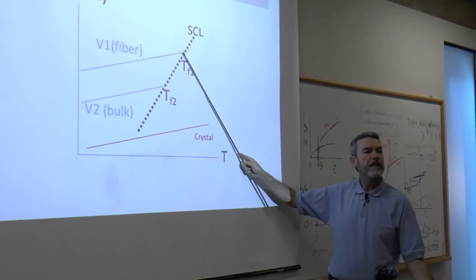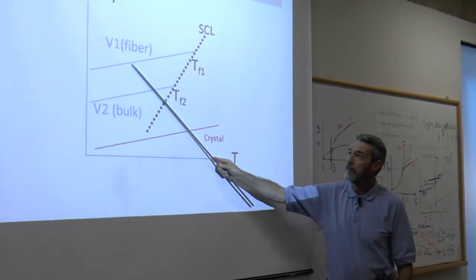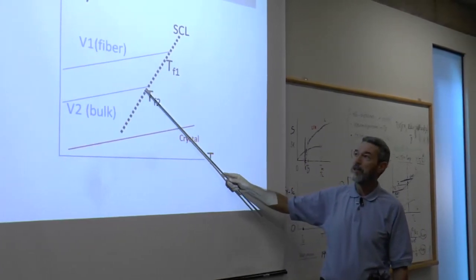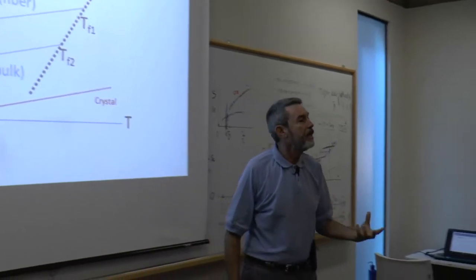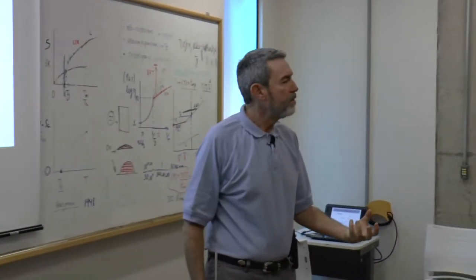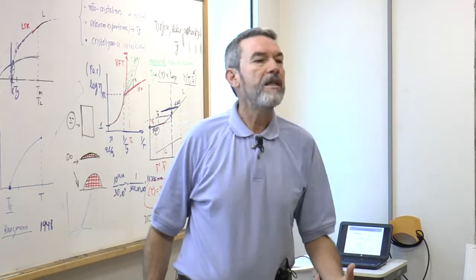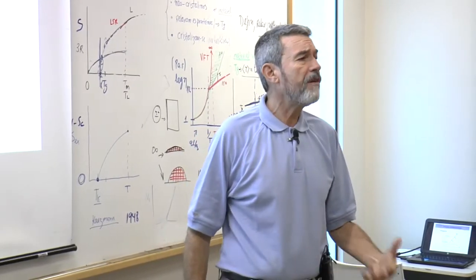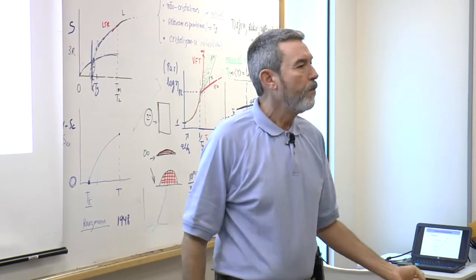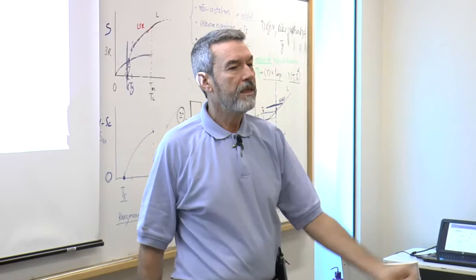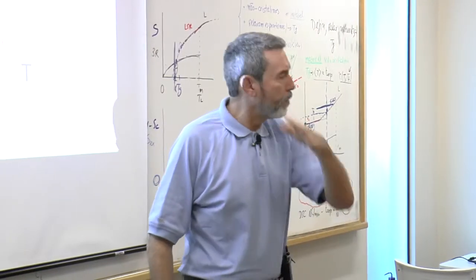Now, if we heat this glass very slowly, it will come here and then relax towards this position here. What I'm trying to say is that TG is close but not identical to the fictive temperature. It can be several degrees off, higher or lower, because we measure TG normally on the heating path in the laboratory. We can also measure TG on the cooling path.